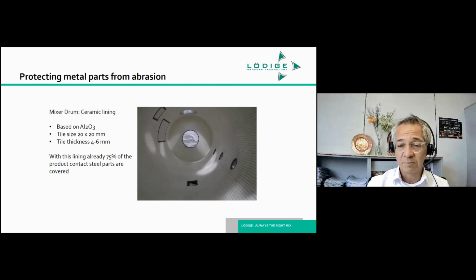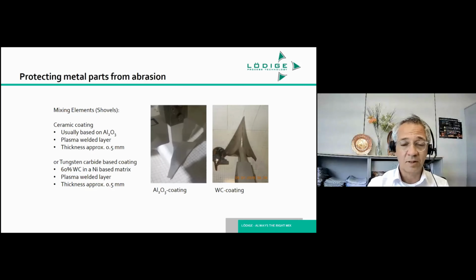But having covered the mixing drum with the ceramic lining only covers 75% of what is in contact with the product. The remaining 25% is made up of the mixing elements, the shaft, and the high-speed chopper units, which are also incorporated into the machine to help distribute the individual components in the overall mixture. And here we've looked into and have used different methods of coating. In the beginning, we looked at, okay, if the drum can be coated with ceramics, then potentially also the mixing tools can be coated with a ceramic layer. Unfortunately, tiling a complicated tool like the plowshare is not really a good idea.